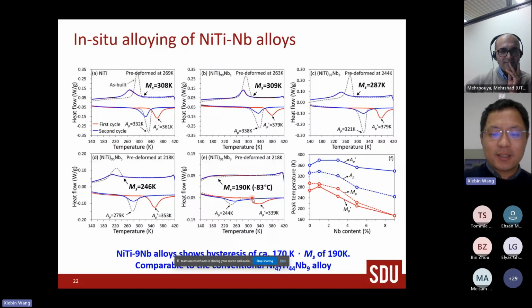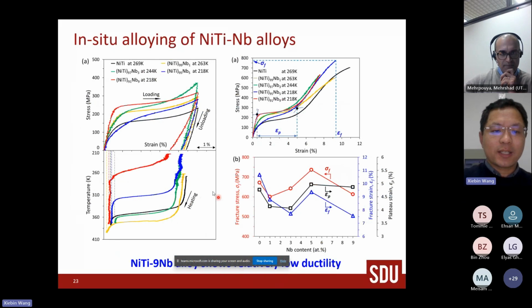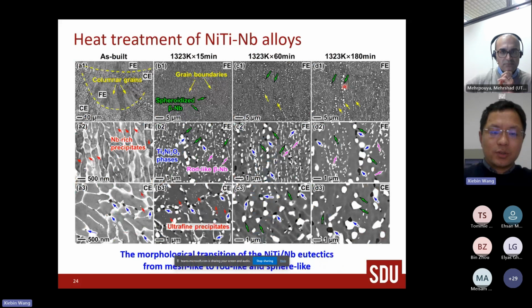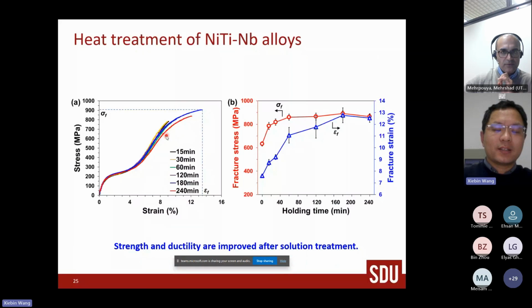So with the addition of niobium, we can widen its thermal hysteresis, similar to the conventional nickel-titanium-niobium alloys, and we checked the shape memory effect. It's a good shape memory effect, but its ductility is not that good. So we do heat treatment to increase its ductility. And after solution treatment, we could increase the ductility to over 12%.